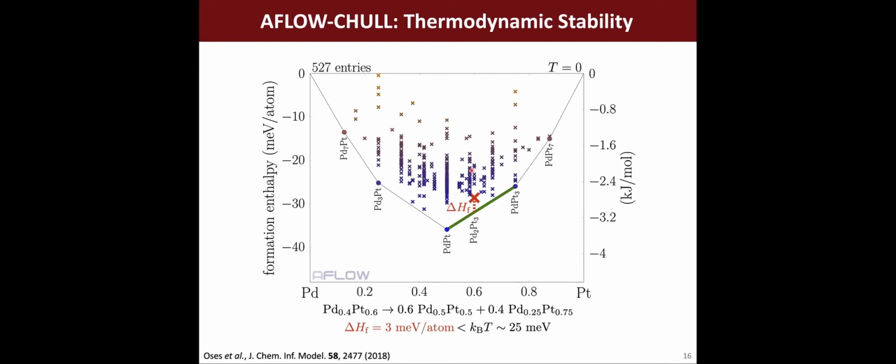And so if you want to understand how the experimental picture correlates with the picture that we have here, you can correlate that, roughly speaking, with this distance. If the distance is very large, you wouldn't really expect that system to form unless there's a lot of disorder, and disorder is driving the stabilization of that material, which we're going to cover in the later session.